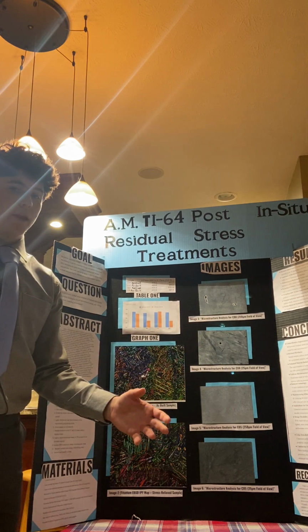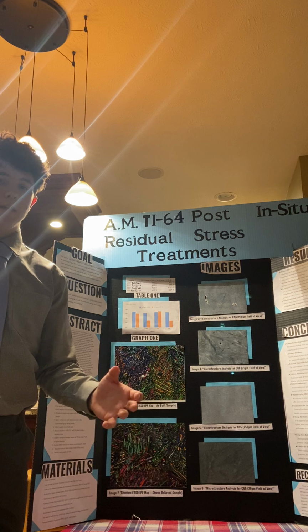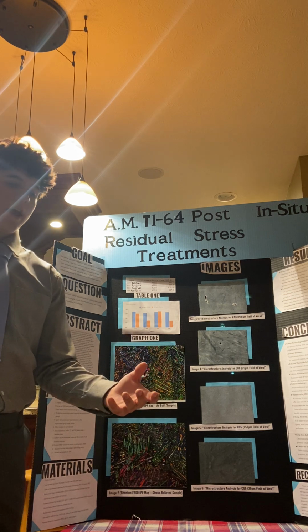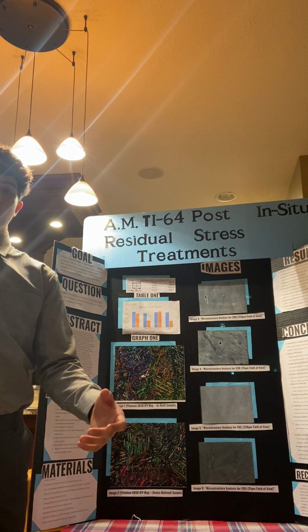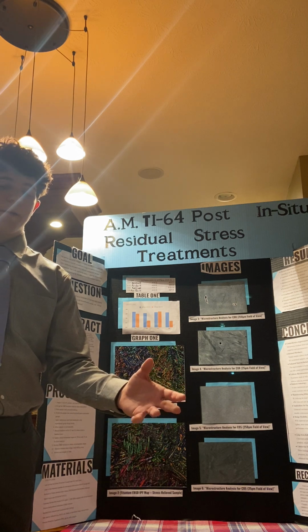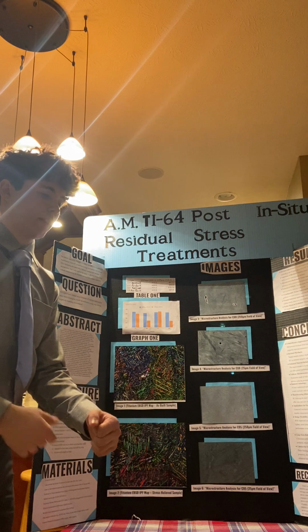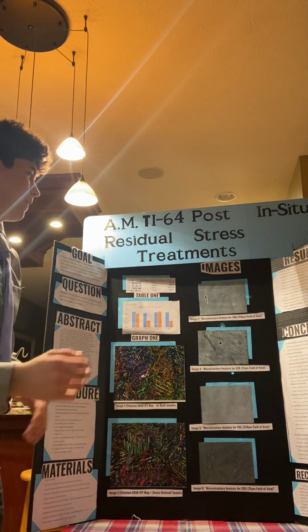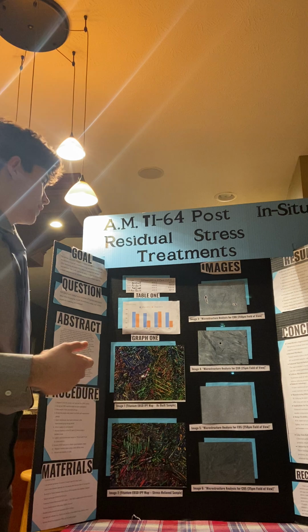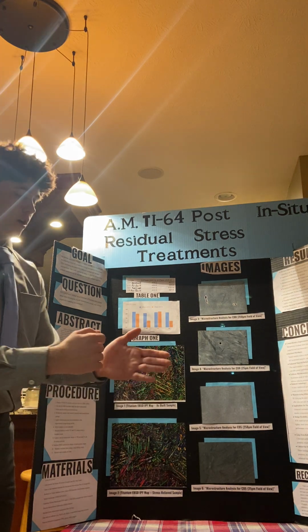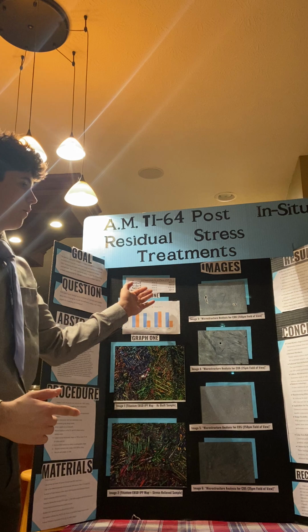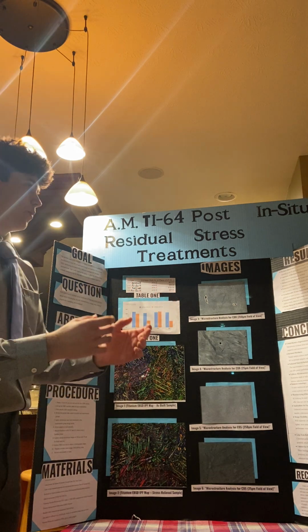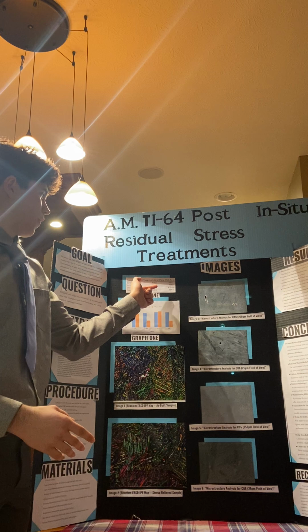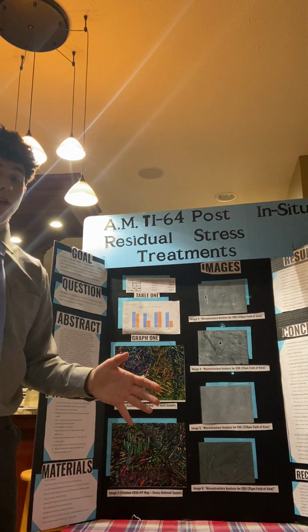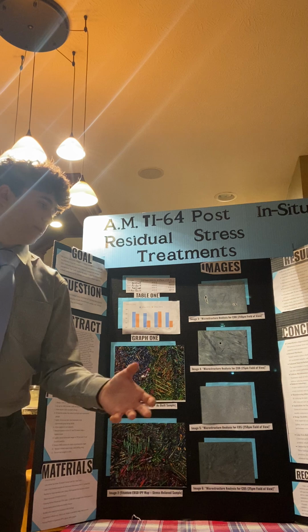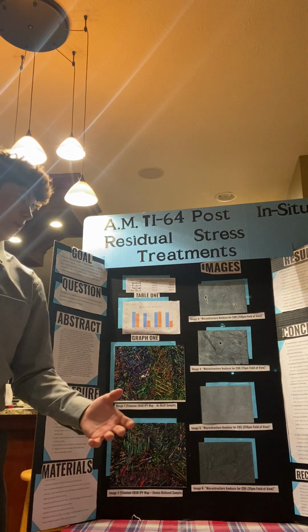Because in movies and things, you see metallurgists hammering knives, swords, whatever material made of metal when it's really hot, they hammer it. That's called hammer peening. What I'm doing with this is laser peening, which is getting rid of residual stress, like I said. And with the laser peening, I believe that it further connected the material to its previous layer, making it have a higher hardness value in the XY plane, which is great news, which is great for further possibilities of the metal, like what it can be used for.